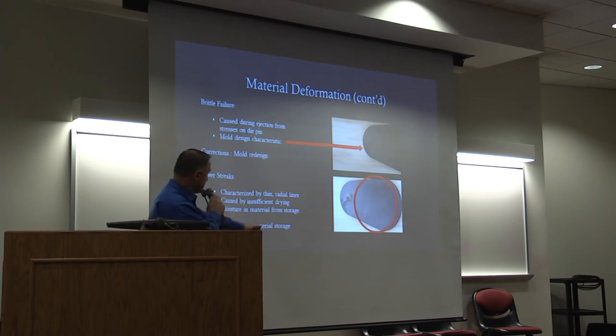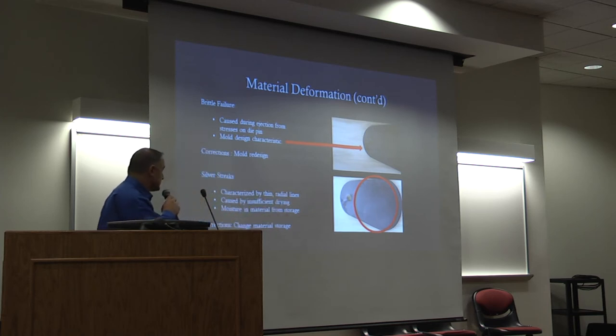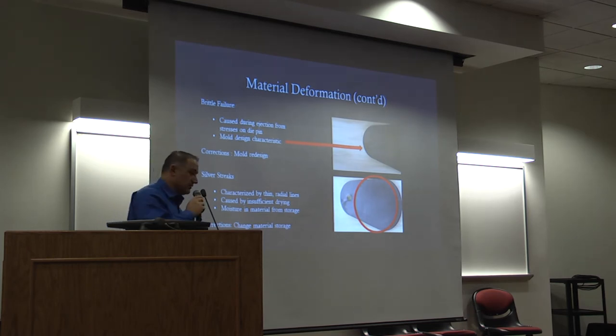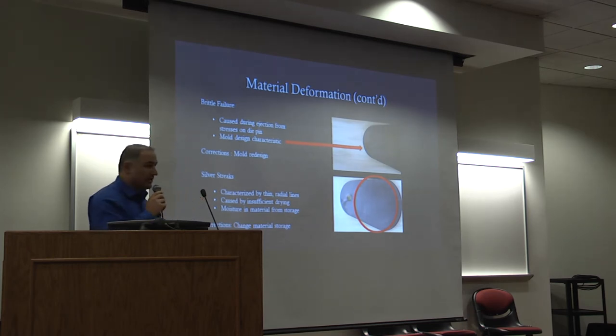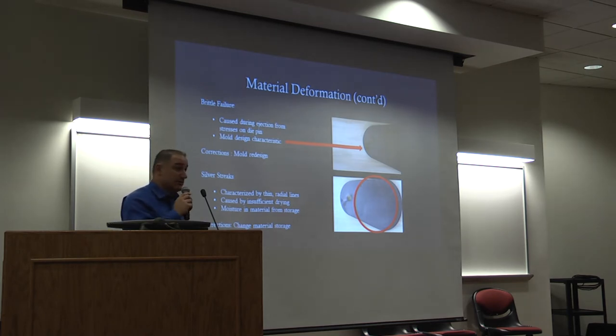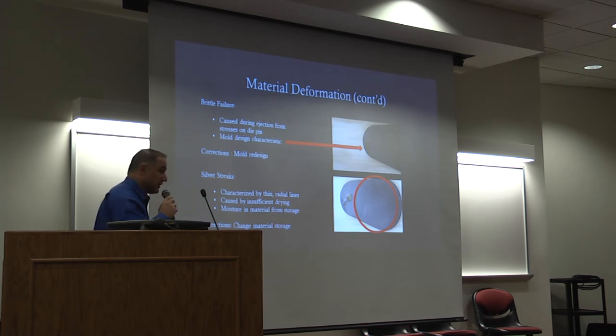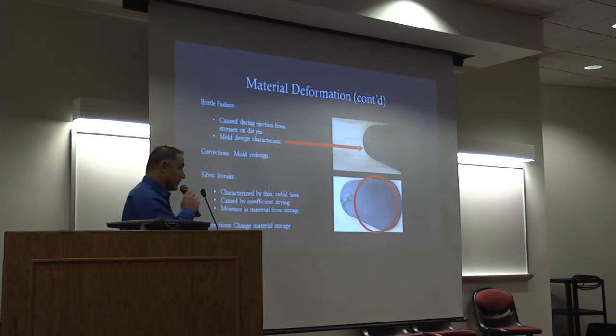Another area is the silver streaking. It's the white radial lines. It's caused by insufficient drying of the material. One of the possible things that we would have, even though polypropylene does not require any drying, is that our material sits in a plastic bag on a cement floor, so it will draw moisture over time. And not knowing how long those materials have been sitting there, possible corrections would be to change our material storing methods.